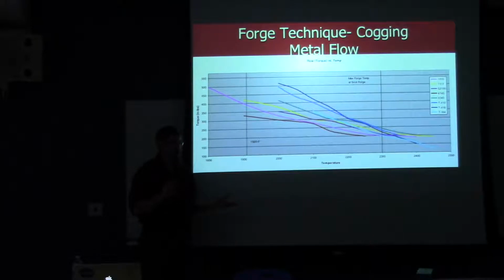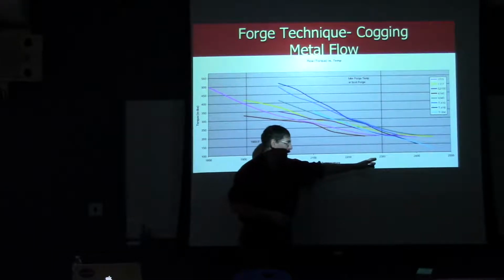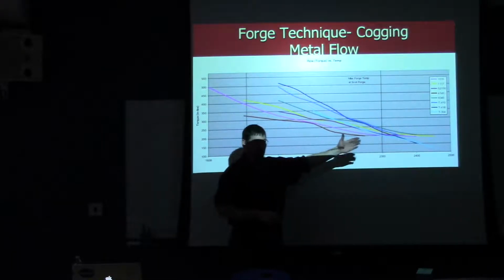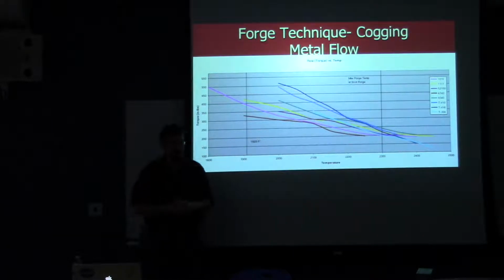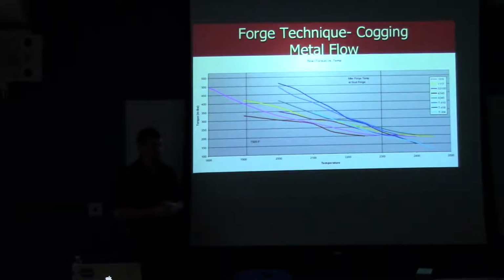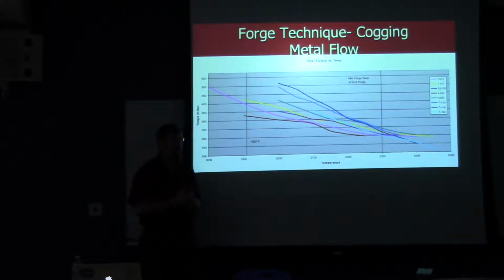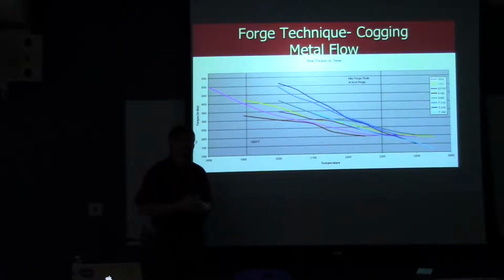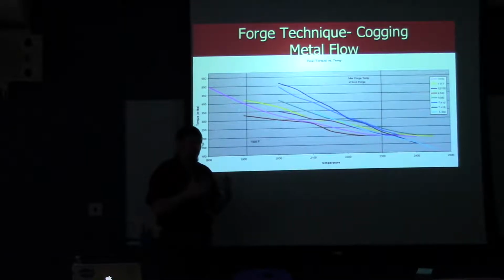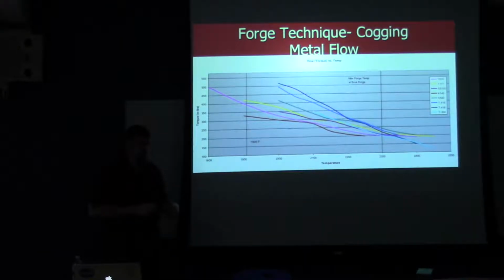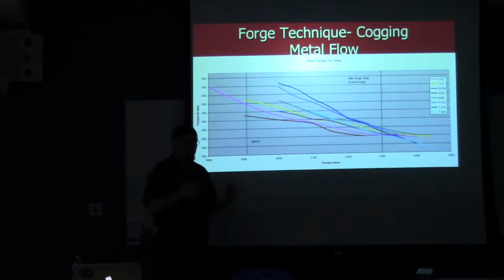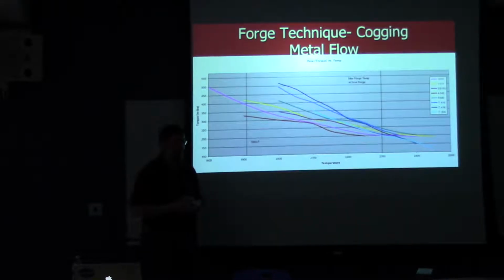Pure iron is going to melt at around 2700, roughly, Fahrenheit. Now, of course, we're nowhere near 2700, right? We're at 2300, so we have a cushion. Why do we have a cushion? Yeah, avoiding melting at grain boundaries. That's very important because we know, as we talked about before, that you get non-uniform composition, so you can have local regions that may have substantially lower melting temperature than what your bulk chemistry would predict. That's an excellent reason. Any other reasons?